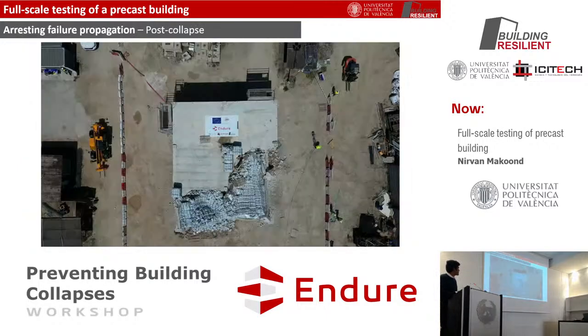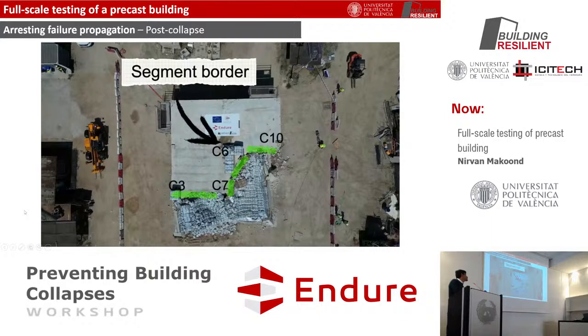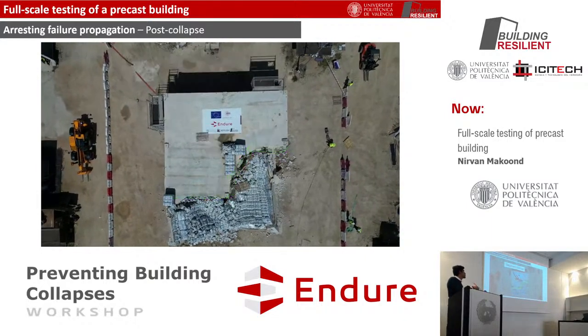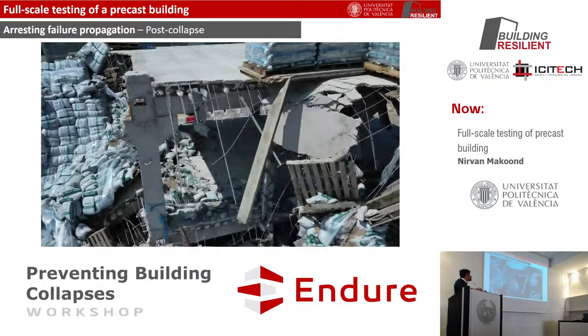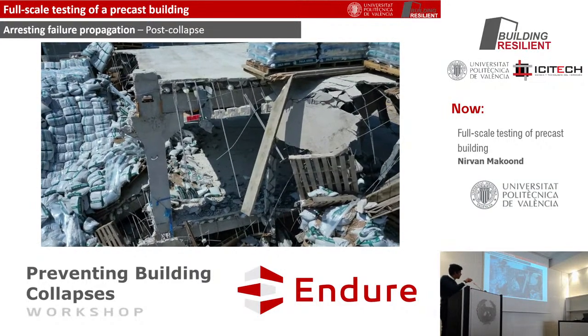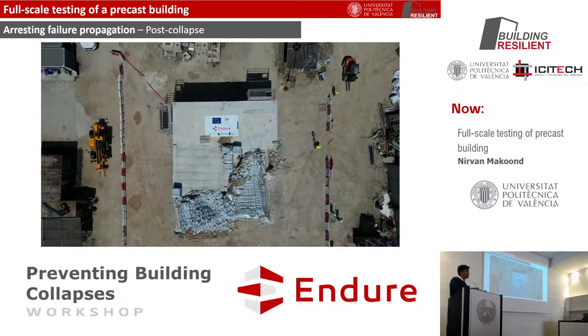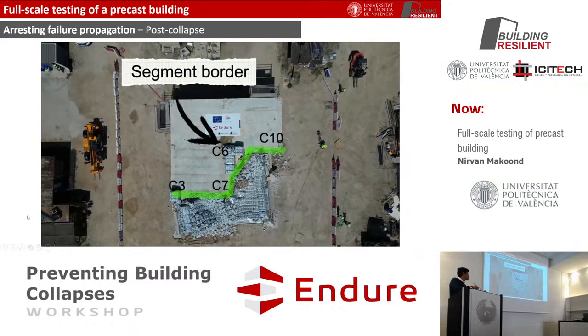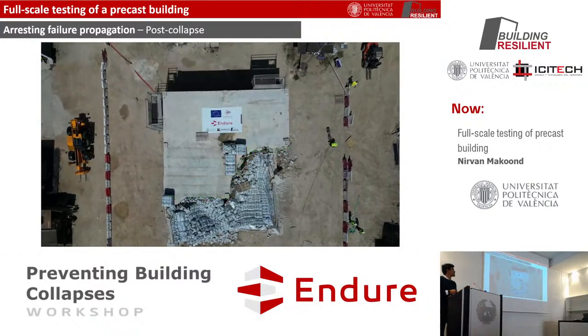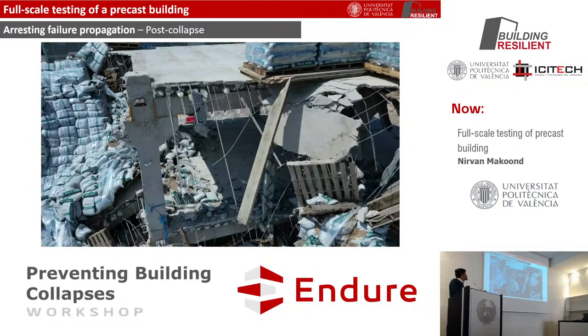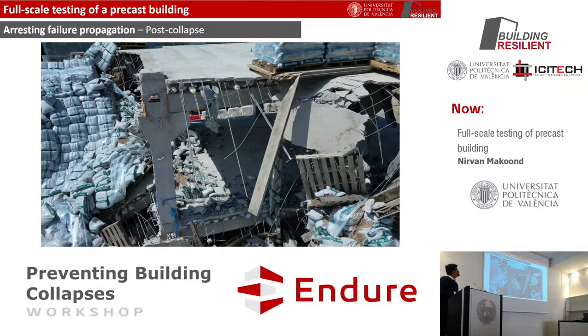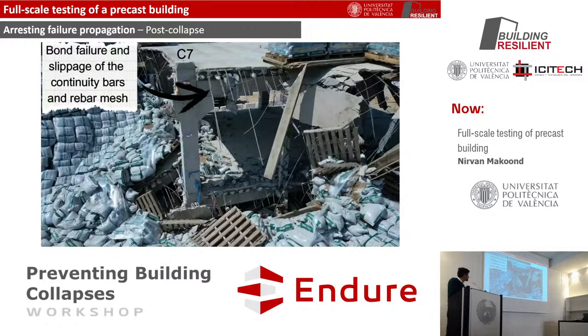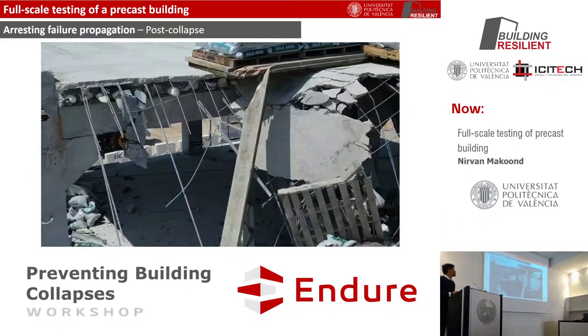And here I would like to show a closer view of the segment border, but also the rupture along the connection, and the debonding in the slab, which enabled the segmentation to happen quite smoothly in this area. So here we can see the debonded rebars in the slab, and the rupture, for example, of the continuity bars here, and the failure and cracking of the corbels, which happened at the connections.